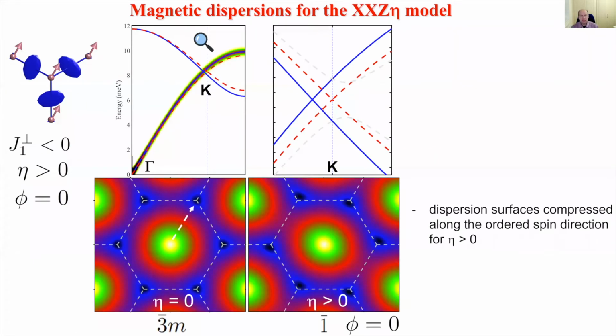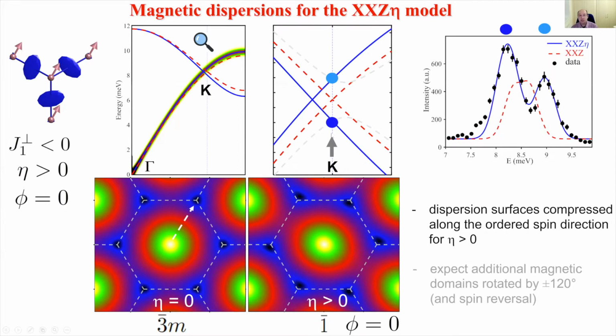And one particular feature here is that in the presence of this anisotropic interaction, the touching points are still intact, but they're no longer symmetry restricted to be at the K point, but they can shift. So in the pure XXZ model, the touching point is exactly at the K point, but in the presence of finite eta anisotropy, this is expected to shift. In other words, the spectrum no longer has threefold symmetry, but only inversion symmetry, and there is a compression of the dispersions along a direction related to the ordered moment. So we expect that the spectrum will shift away from the K point. So then, by doing a scan exactly at the K point, one would expect to see a splitting, so two peaks rather than a single peak.